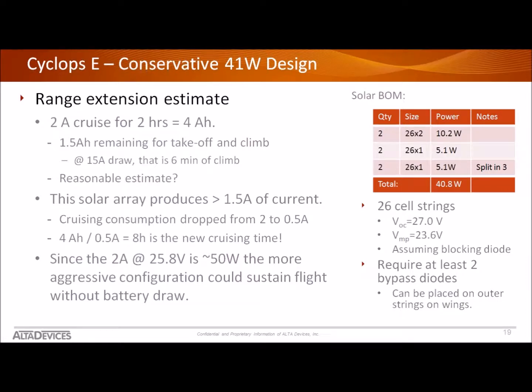So using our estimate of a 2 amp cruise, if we have about a 2-hour flight time from what's been communicated to me, that would use about 4 amp hours of the 5.5 amp hour capacity of the battery. So that gives us an additional 1.5 amp hour remaining for takeoff and climb, which at about a 15 amp draw, that's about 6 minutes of climbing, which seemed like a very reasonable estimate to me. Now, of course, the users who are more familiar with UAVs could potentially help us find better estimates for power draw when we're coming up with these designs. And the more information we get from you guys, the better we can come up with the right solution.